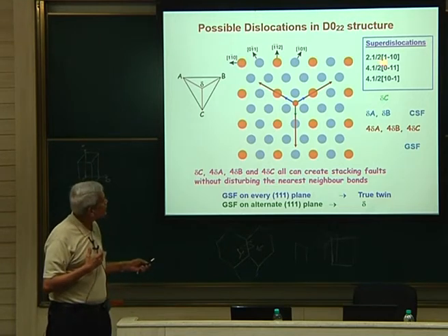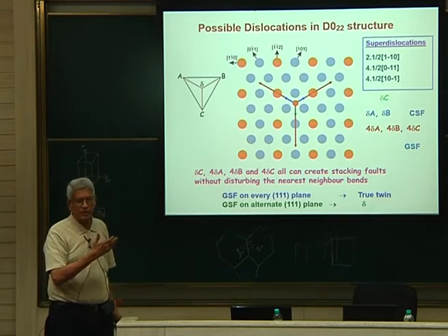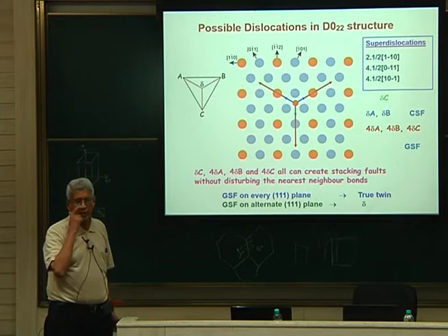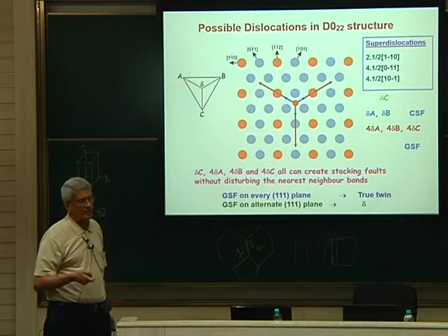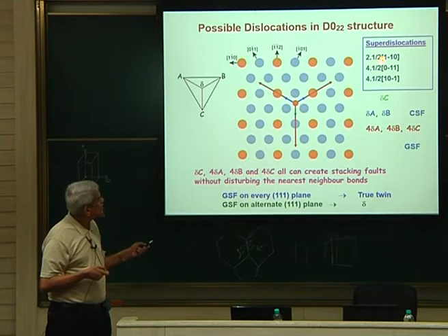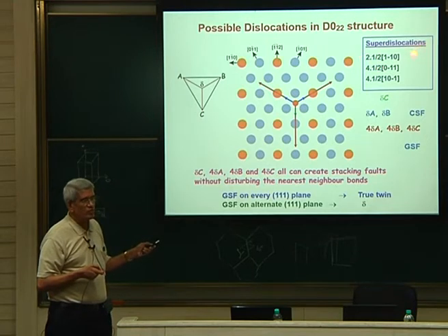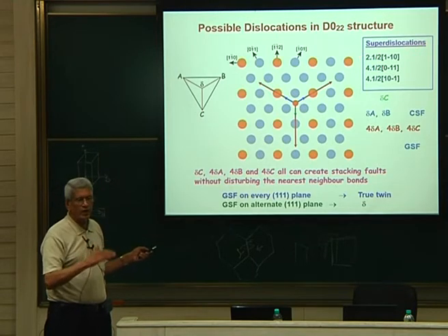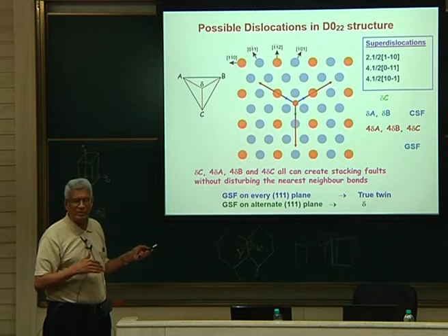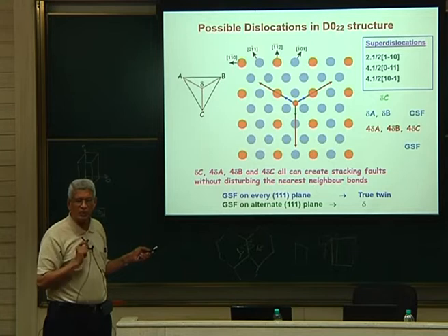So if this dislocation splits, because the precipitate volume fraction is very small and most of the dislocations are generated in the matrix, 2 matrix dislocations with the same Burgers vector passing through is equivalent to a superlattice dislocation with an antiphase boundary in between them.